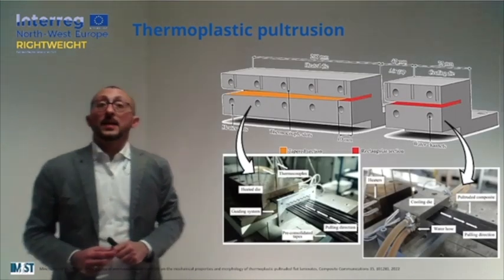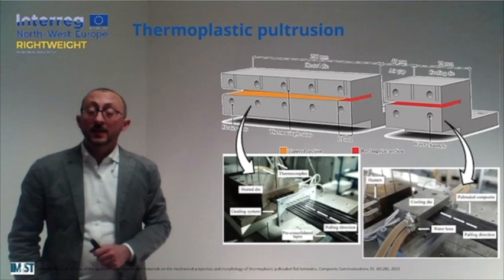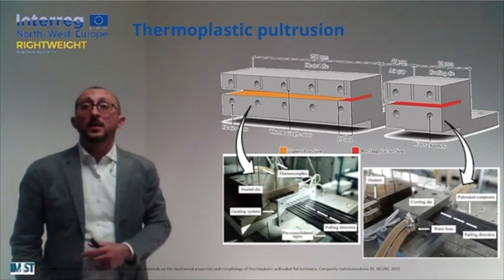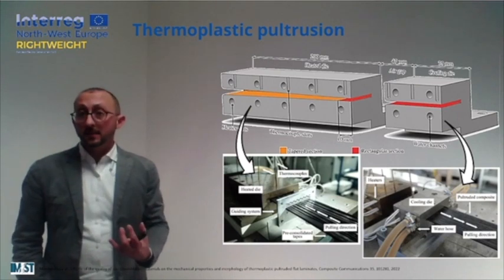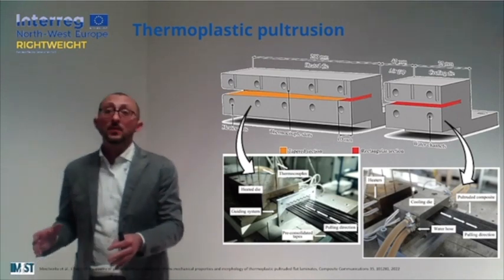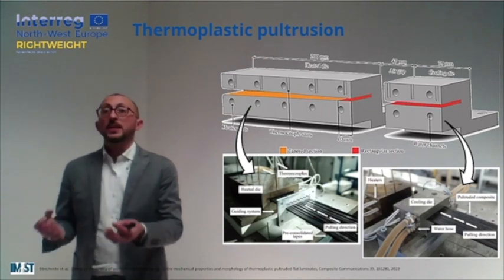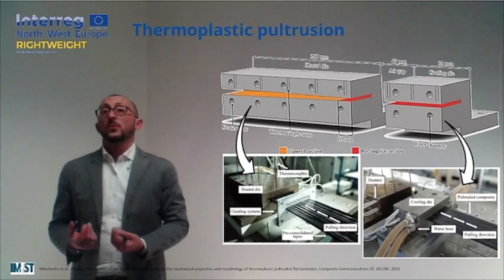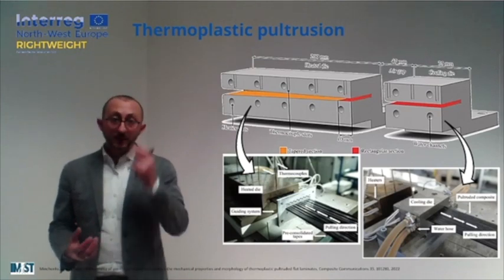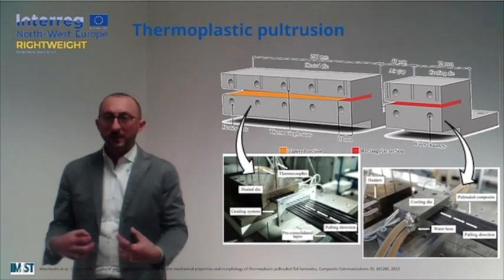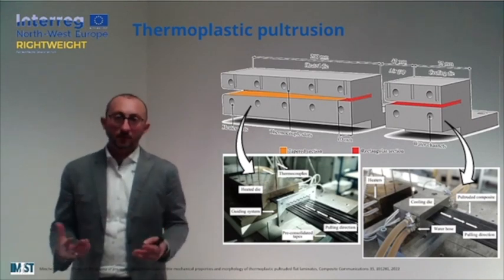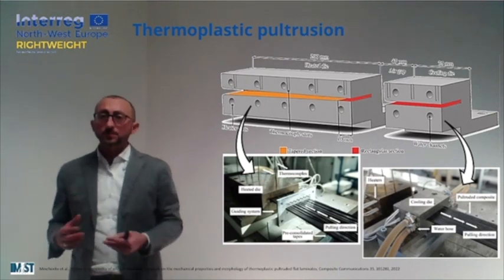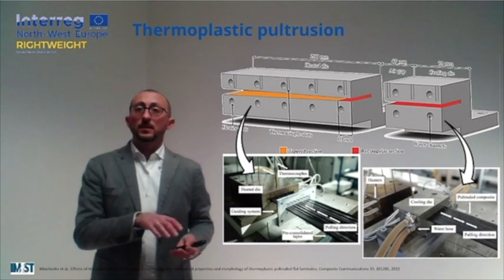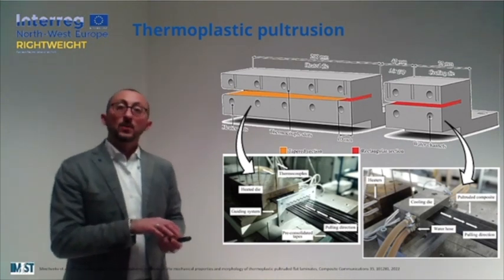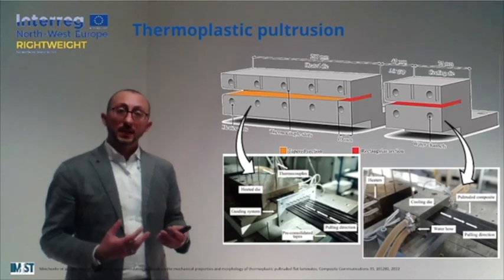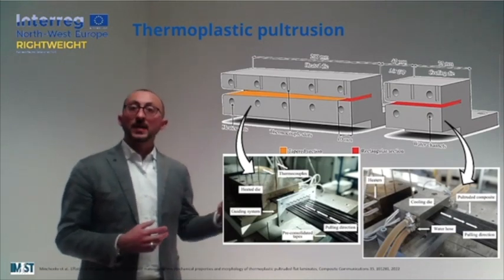So in this case, our pultrusion die is characterized first of all by the presence of a heated portion at the beginning of the die, where the material will be heated up, and this increase in temperature will promote some melting of the thermoplastic resin, some kind of flow and proper wetting. The eventual excess of resin will be wiped out, and then when the straight cross-section of the die is approached, we can slowly start cooling down the die itself and the material.